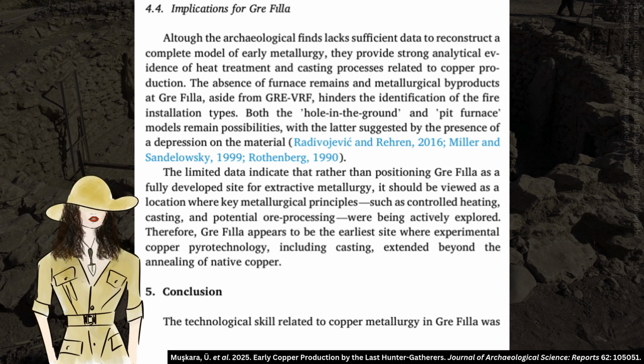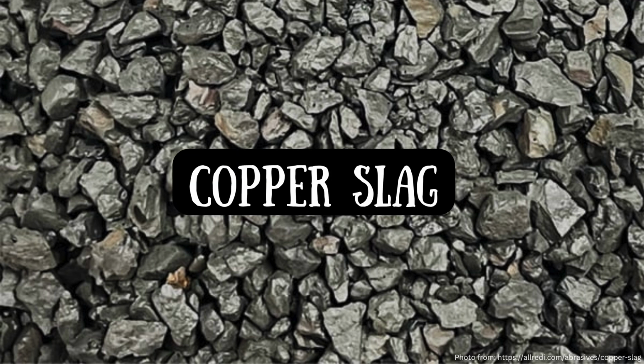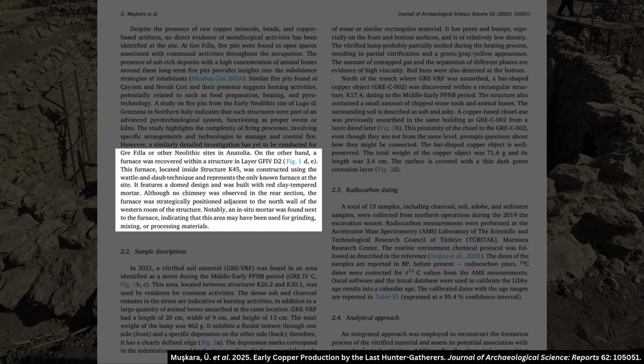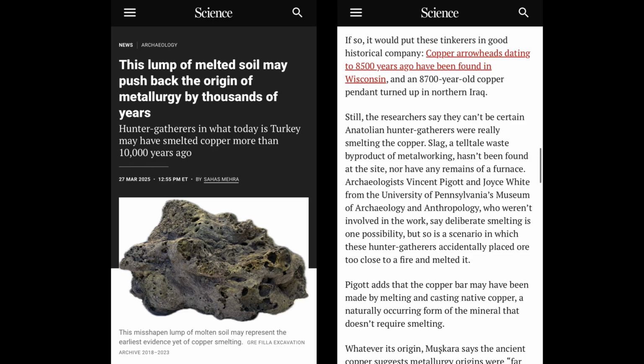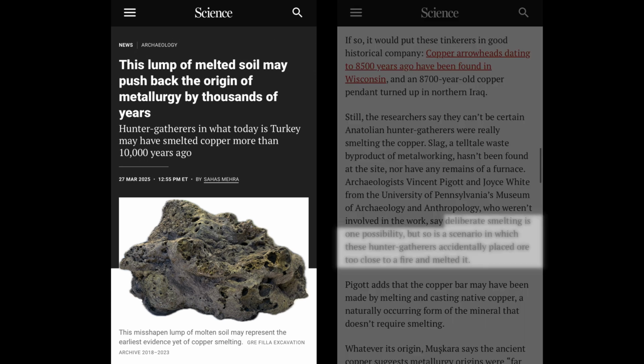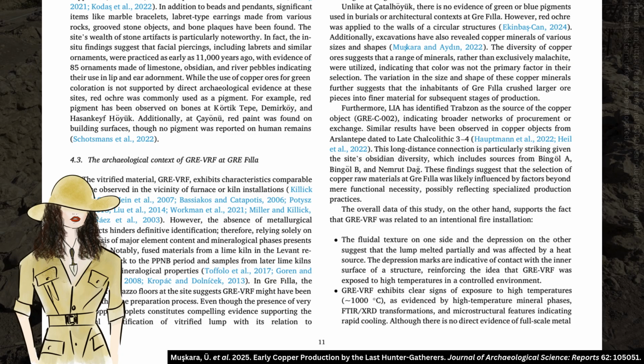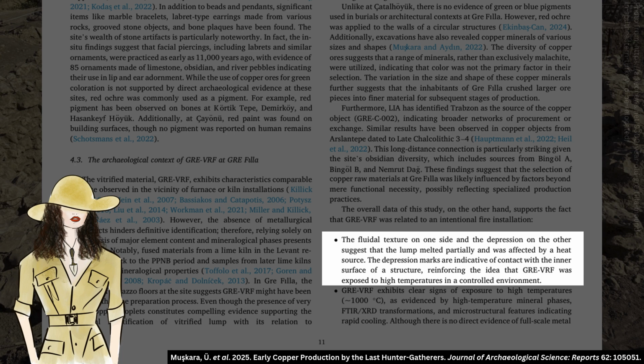However, in light of these new findings, I think the idea that people were experimenting with pyrometallurgy more than 9,000 years ago should be taken seriously. Sure, archaeologists haven't found slag there, a byproduct of the smelting process and thus a telltale sign of this kind of pyrometallurgical activity, and the function of the one furnace that has been found at the site hasn't been established with certainty, but it doesn't seem likely to me that the vitrified soil material resulted from copper melting after an ore was accidentally left too close to a fire, as has been suggested, since the surfaces of the material provide evidence that it was exposed to heat while in contact with the inner surface of a structure, likely some type of fire installation. This is more suggestive of experimentation with pyrometallurgy as opposed to a mere accident.